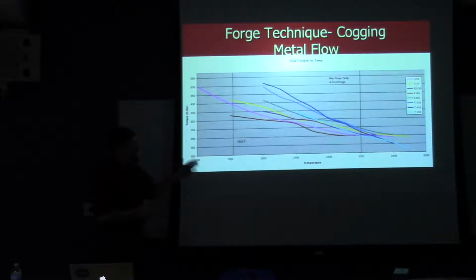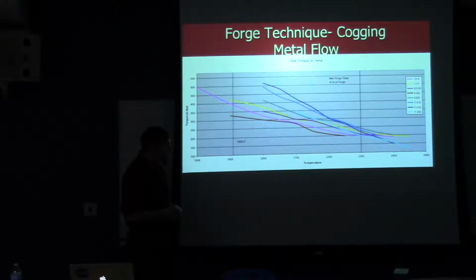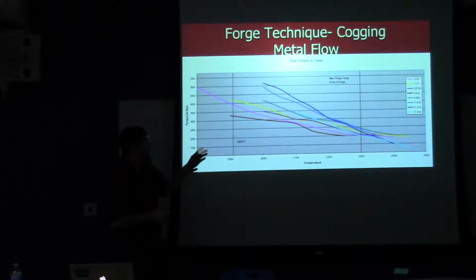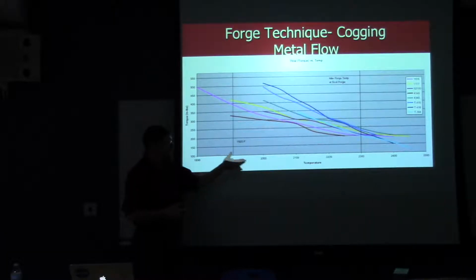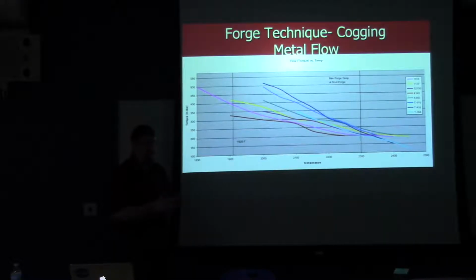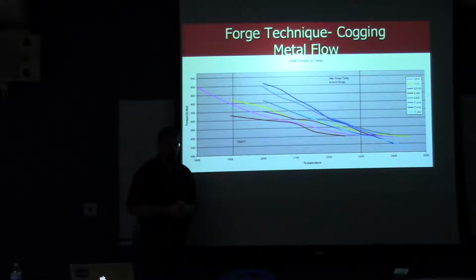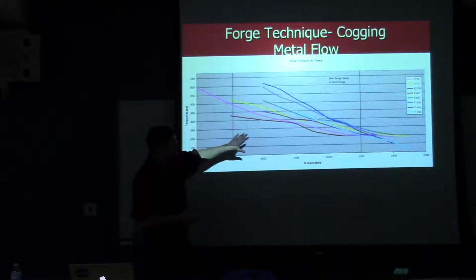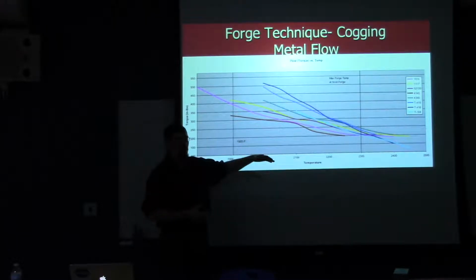So you do the test, you do it at all different sorts of temperatures, and you measure the torque. And you can see here that you get lower torque at high temperatures, higher torque at lower temperatures. That's sort of an intuitive thing. You probably figured that out by some of the forging that we've done already. When the metal's cold, it doesn't move as easily as when it's hot. But this also lets us see how different materials compare with one another.